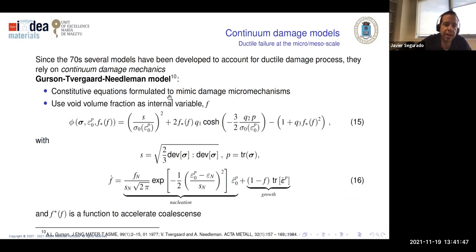Okay, so what we have is a yield function. This is just pure von Mises, J2, and it adds some terms, and the terms depend on the porosity f. So when f increases, the yield locus gets smaller and smaller, so the load carrying capacity of the material decreases. And we have the yield, but we need also some ingredients to see how this volume fraction of porosity evolves, and we have in the original model 2 ingredients. One is nucleation, so we have smaller precipitates or grain boundaries, non-visible at this length scale, that produce the nucleation of porosity, is this part, and we also have growth.